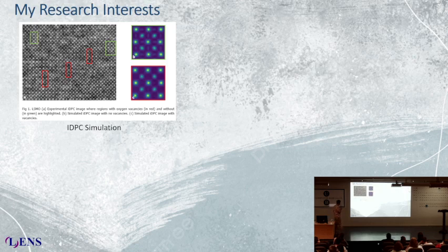So from here, if you look very closely, I will try to point it out properly. There are some spots like these, 1, 2, 3, 4, which are missing here, right? What you can see is that these little ones, not the brighter ones, actually correspond to oxygen. So now I can tell you that in your sample, you have some areas which lack oxygen, or have oxygen vacancies, and in some you don't have oxygen vacancies. So this is a part of my work.